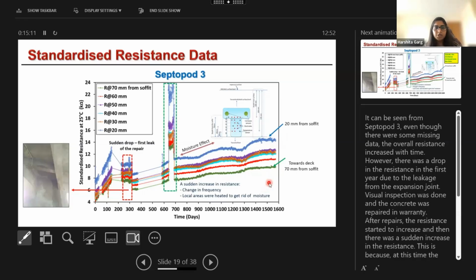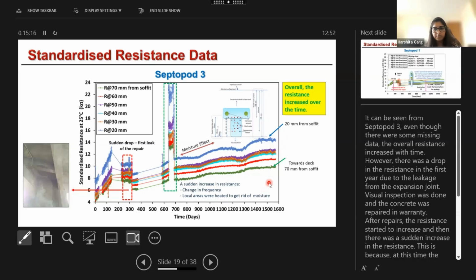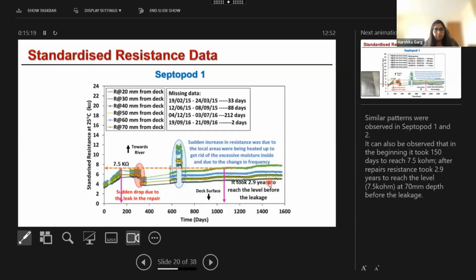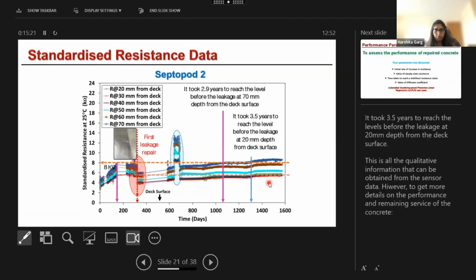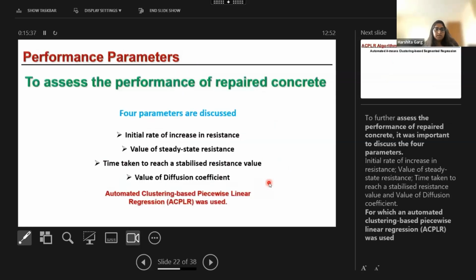So this is all the information that we can get from pre-processing the data, which is a qualitative kind of information. Similar data we got from Septopod 1 and Septopod 2. But in order to get further information about the performance of concrete and remaining service life, we need to quantitatively analyze this data, for which now we need 4 different parameters. First is the initial rate of increase in resistance, then the value of steady state resistance, the time taken to reach the steady state resistance value, and finally the value of the diffusion coefficient.